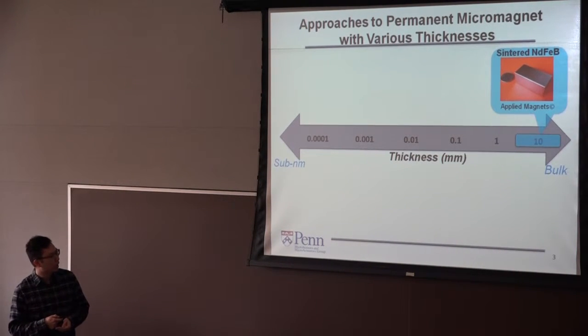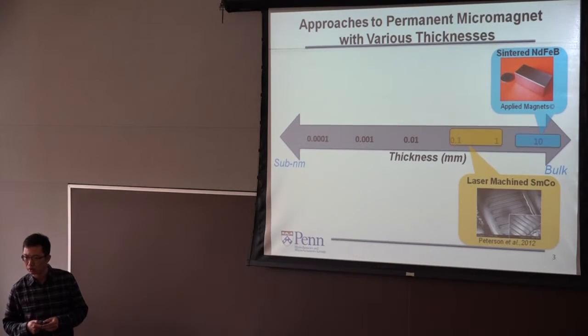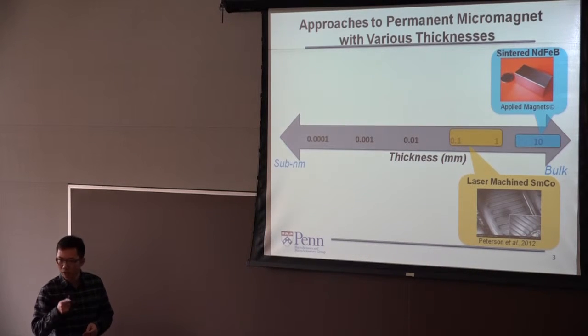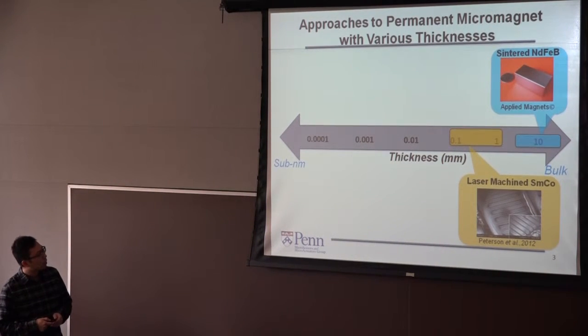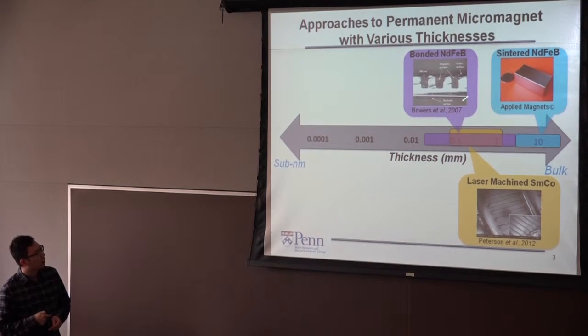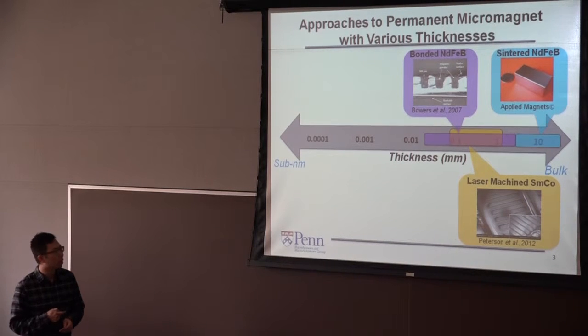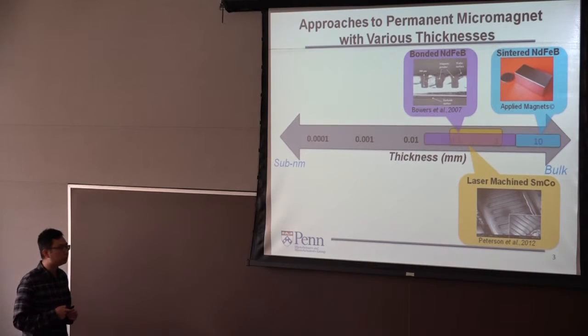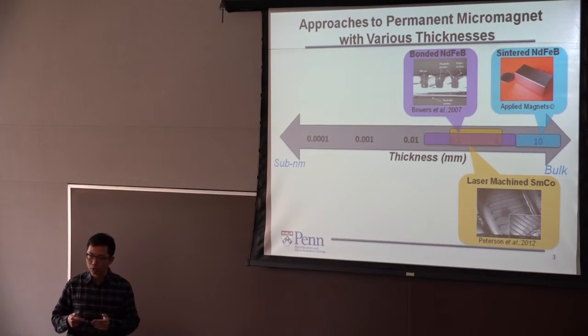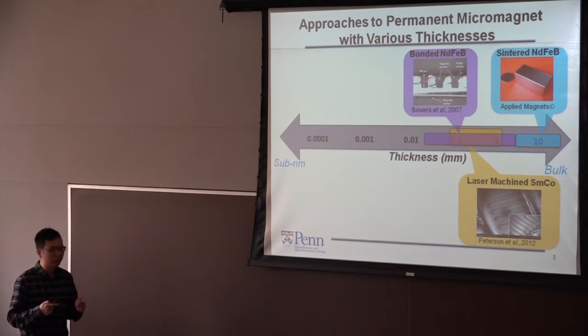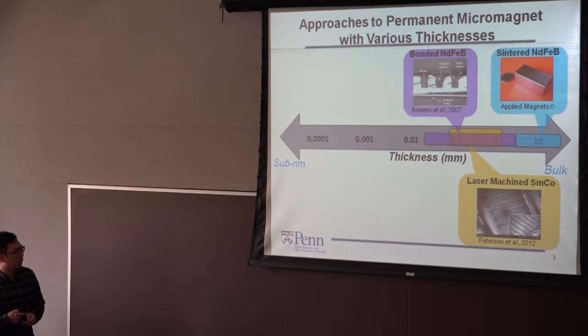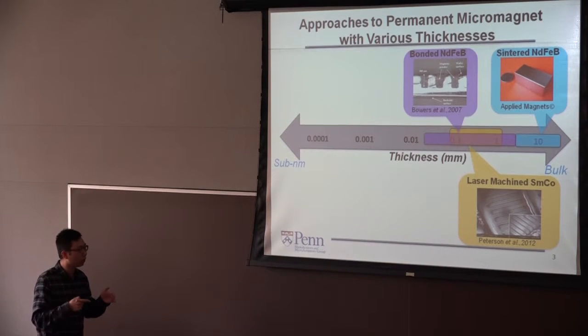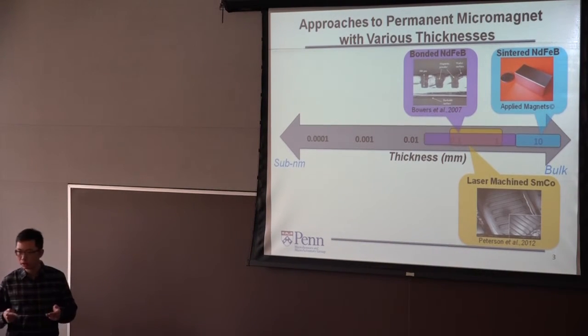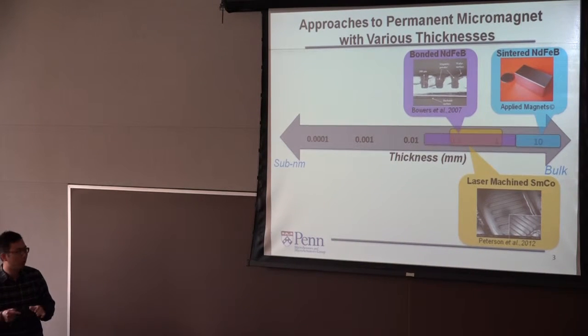So one way you can still utilize the sintered magnet is by further processing it. For example, you can do laser micromachining, and we have an expert in our group to do this. In a similar length scale, you can use the bonded magnet. It's called a bonded magnet because it uses magnetic powders. They load the powders into a certain polymer, and then you can use different techniques. Either you do a screen printing-like technique, you lap it into prefabricated trenches, or you blend this powder with photosensitive polymers, and then you can use traditional lithography to define it. The powder is normally in micron size, tens of micron size.